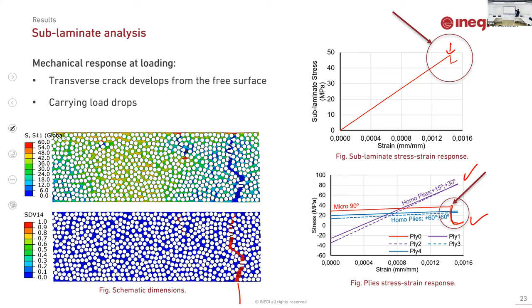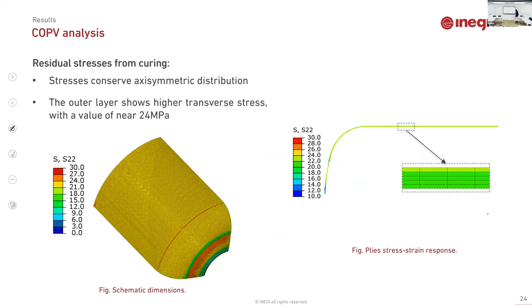If we have a bigger laminate, this change is small. But if we look at the local part, we see that one lamina breaks and is not capable of sustaining more load. If we have a fluid, the fluid will permeate through these crack leakage paths. This part was considering the sublaminate model.